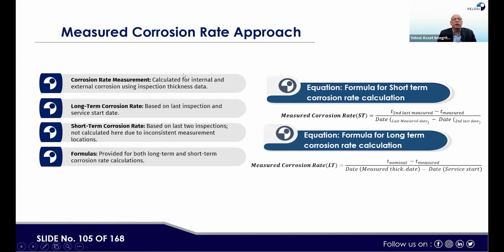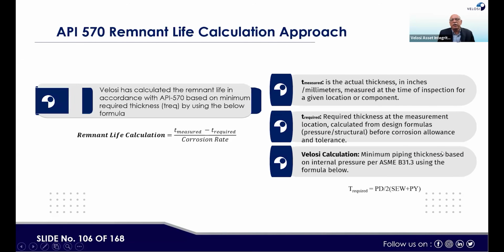Then corrosion rate measurement: long-term corrosion rate is there, short-term corrosion rate is there, and formula-wise, the measured corrosion rate uses the second last inspection thickness minus T measured, divided by the time period between them. So the same formula applies, whether we are taking two inspections or an interval from the last inspection to the startup, which could be a long term. The metal loss between two inspections and the duration between two inspections is basically the short-term corrosion rate. Then we calculate the remnant life as T measured minus T required, divided by the measured corrosion rate. Then accordingly we can see the remnant life of the equipment.